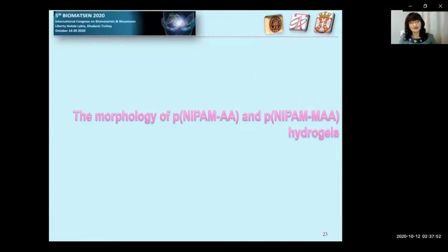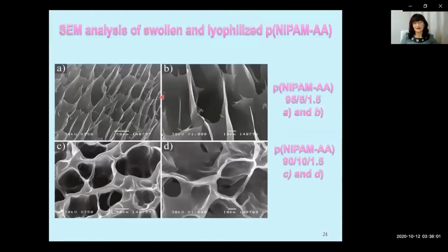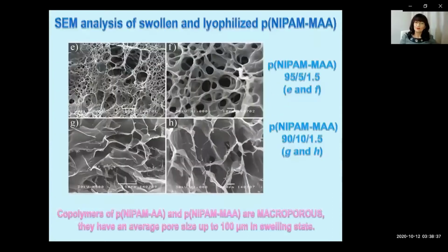The morphology of swollen and lyophilized hydrogels was analyzed using scanning electron microscope. Morphological disorganization and the presence of large pores are observed in the micrographs of poly(N-isopropylacrylamide) co-acrylic acid with 5 and 10 molar % of acrylic acid. The three-dimensional hydrogel network provides a large free space between cross-linked chains in the swollen state. All micrographs show characteristic porous surface and microchannels which facilitate water absorption. Similar morphology can be seen in the micrographs of swollen and lyophilized copolymers with 5 and 10 molar % of methacrylic acid.